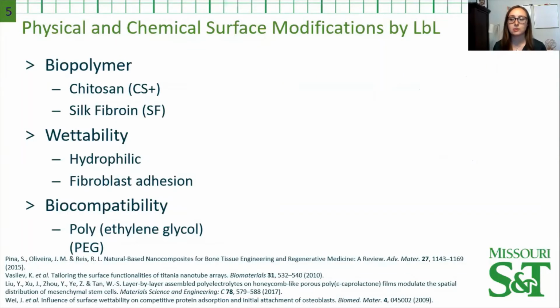So in the core, we would use PVA, while in the shell, we would use a PCL-SF blend. Here's a cross-section of what the morphology would look like. A bioactive organic layer, like chitosan, is commonly added to the surface of a synthetic biomaterial to reduce the time for osseointegration, increase cell growth, and improve the hydrophilicity.